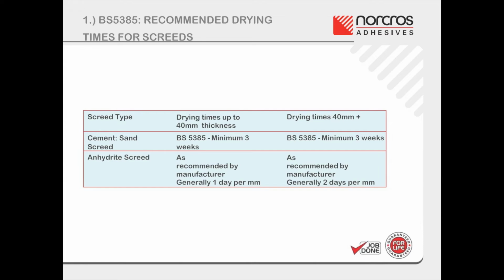The time taken for anhydrite screeds to dry is generally around 1 day per millimetre up to a thickness of 40 mm, with an additional 2 days per millimetre above 40 mm. However, this will vary between brands, so it is best to seek the advice of the manufacturer. It should be noted that the removal of laitance will help to dry the screed.